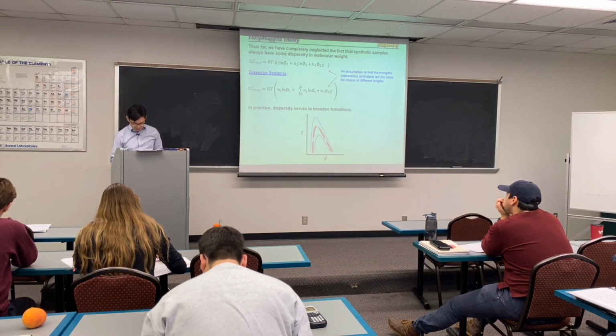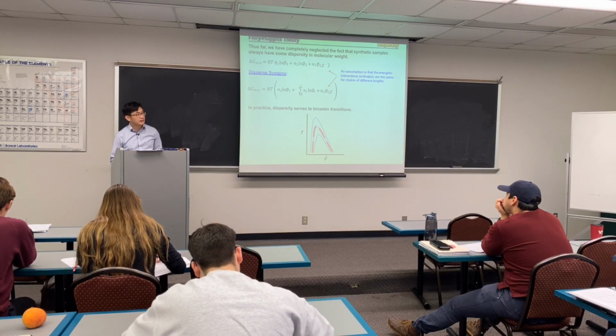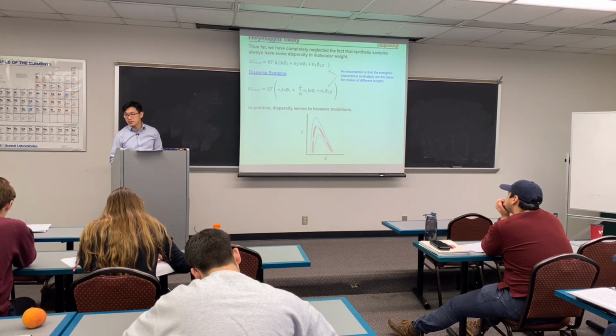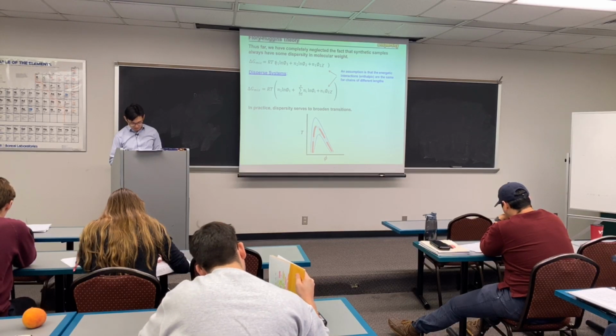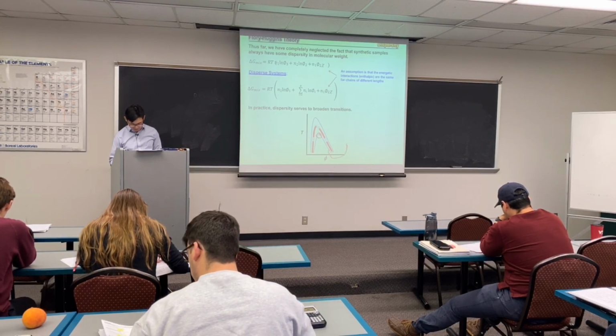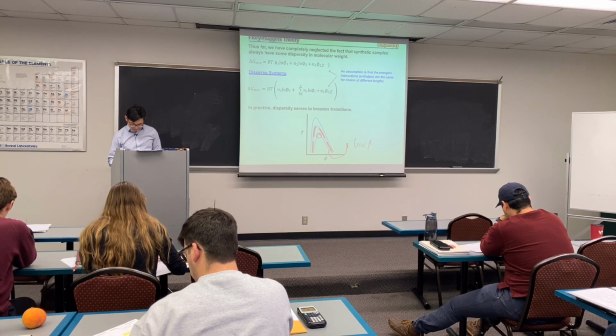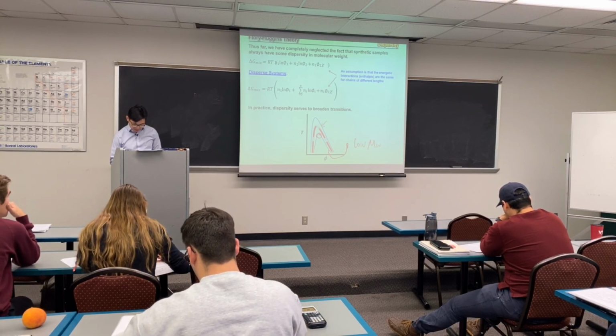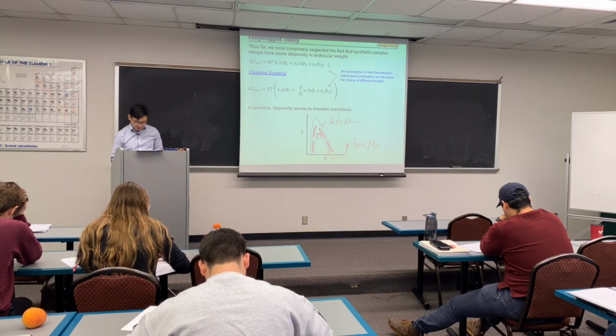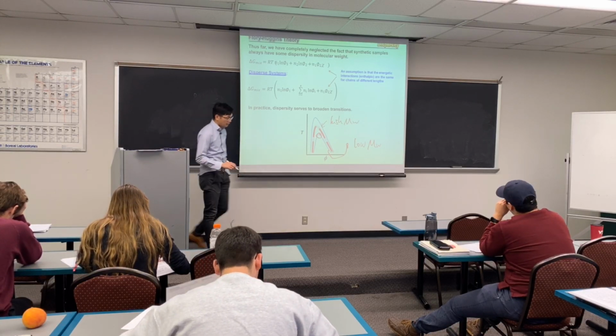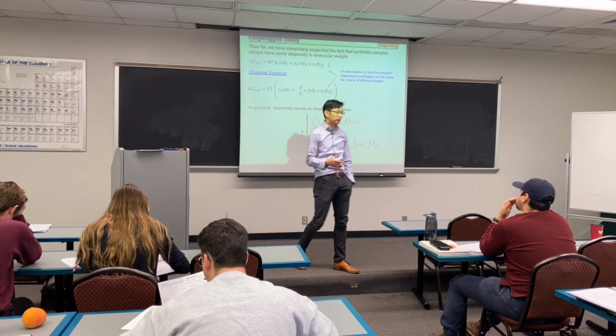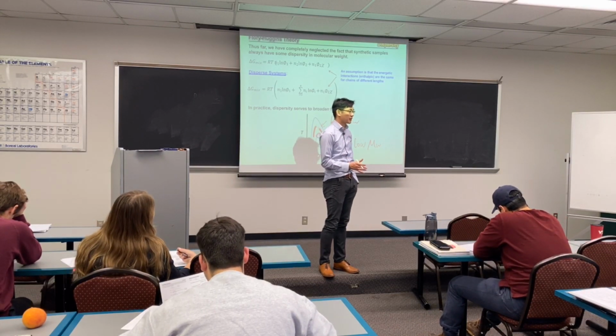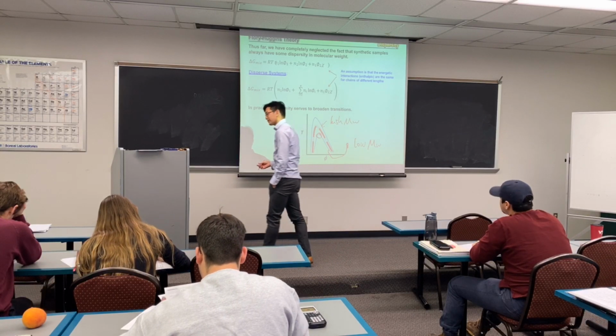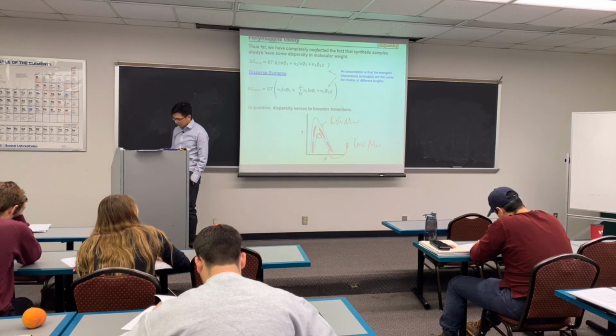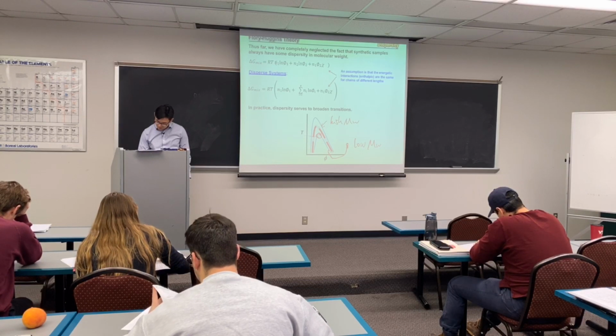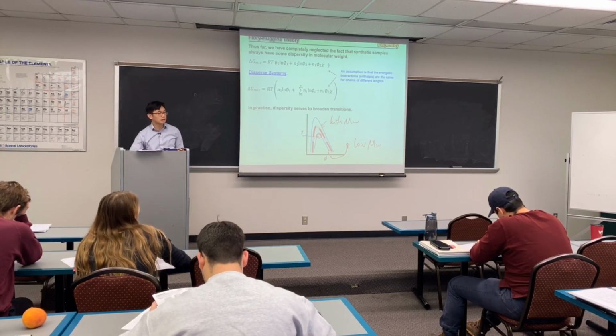This is where you have T versus phi. If your polymer has different contributions in the phase diagram, the low molecular weight, which is the case shown in this line, will phase separate quite differently from the high molecular weight. So you would have quite an interesting system where some of the material has already phase separated, but some is still dissolved. If you want to drive everything into the two-phase region, you have to lower the temperature to this point, which is related to the lowest molecular weight.